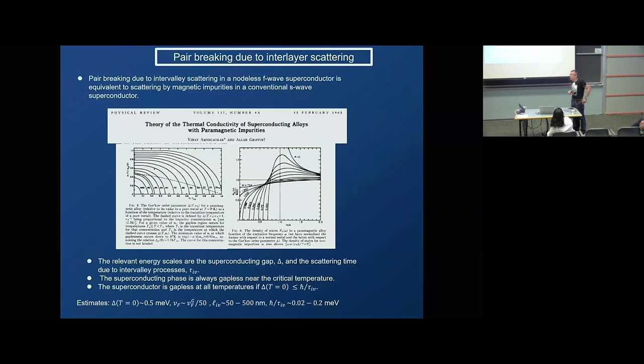If you have disorder, any type of disorder, in the case of the F-wave superconductor I have described to you, elastic disorder plays exactly the same role as magnetic impurities in an S-wave superconductor. And that can change a lot the type of superconductivity you observe. But in order to make this more quantitative, you need things like the mean free path and stuff like that, which are not very available.